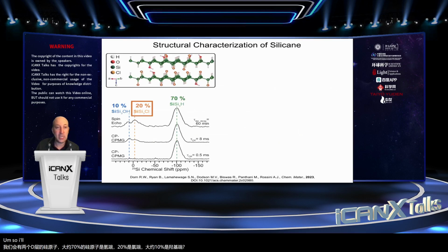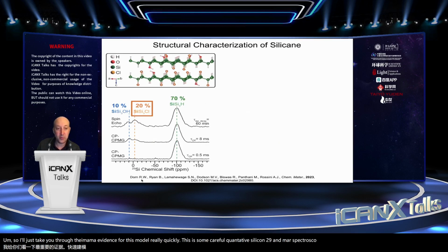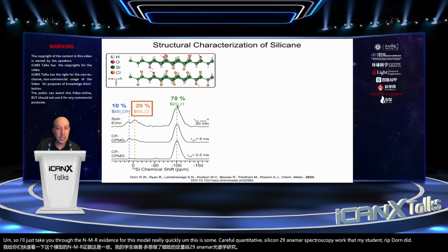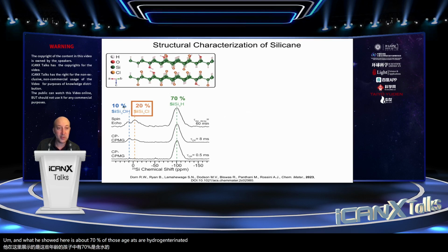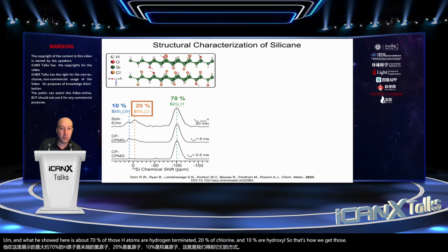So I'll just take you through the NMR evidence for this model really quickly. This is some careful quantitative silicon-29 NMR spectroscopy work that my student Rick Dorn did. And what he showed here is about 70% of those silicon atoms are hydrogen terminated, 20% are chlorine, and 10% are hydroxyl. So that's how we get those proportions.